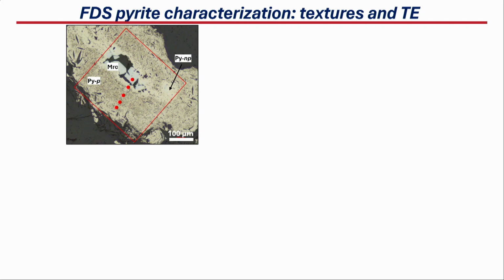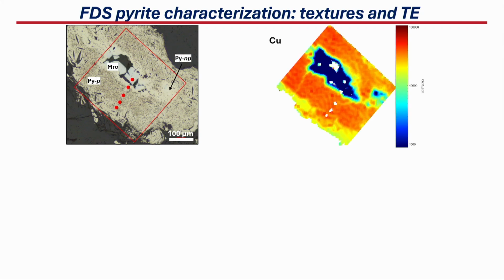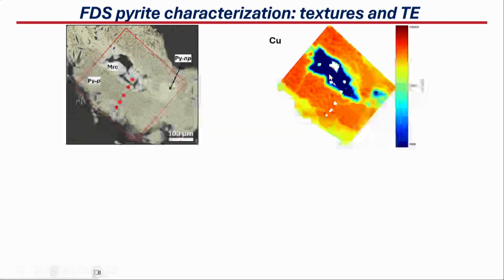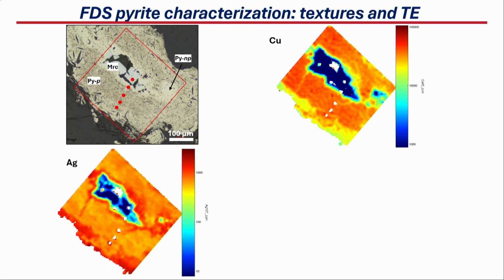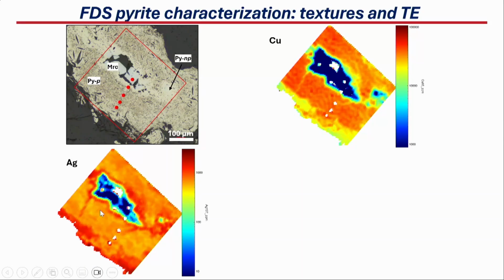What we obtain for these copper, gold, and silver metals is that if we see the copper distribution, this porous pyrite is really high in copper. We can get up to 4 weight percent copper, as I mentioned. Of course, we do have some areas where we have lower values, and the marcasite essentially doesn't have any copper. Then if we see silver, it's not completely correlative with copper, but still presents up to 1,000 ppm in this region